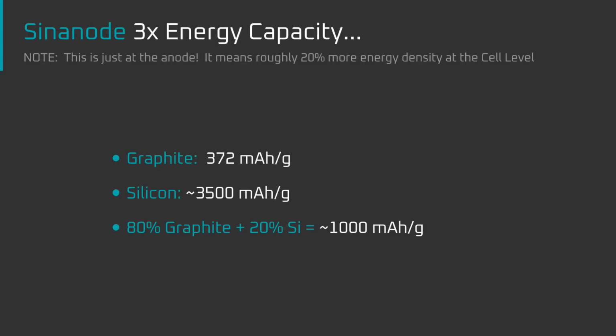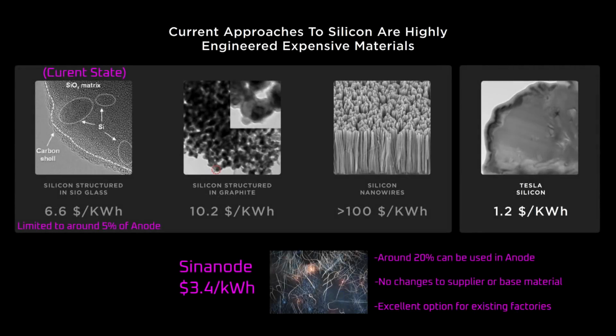What happened is that the combination, the composite of the graphite plus the 20% silicon nanowires has a reversible capacity around 1,000 milliamperes per gram. So you have triple the energy, the specific capacity of the graphite. And that basically decreased by about half the cost. So you end up with about the cost about $3.4 per kilowatt hours.